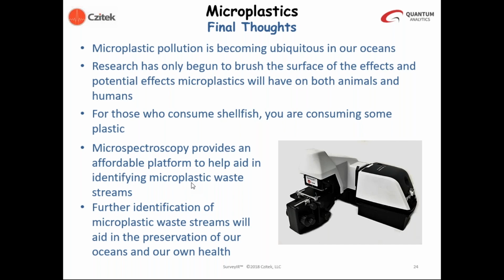Great. Another question is, how do you determine which measurement mode is best for your sample analysis, like ATR, reflection, or transmission? Once again, that will depend on your sample. We would want to try to use ATR as frequently as possible due to its ease of use, and you're going to get a high quality spectrum with a very reproducible or uniform thickness, because the thickness, as I said, is determined only by the optical properties of your sample and the diamond element. So we try to analyze samples in that mode if we can.